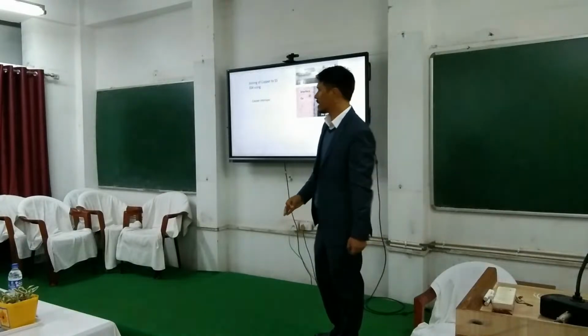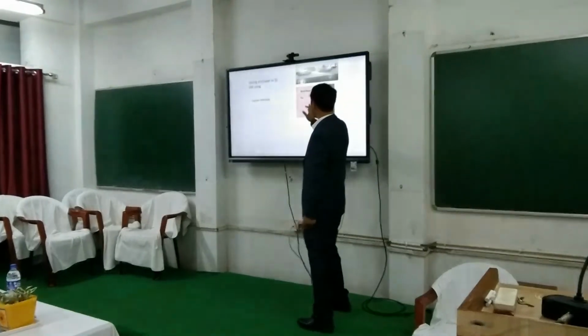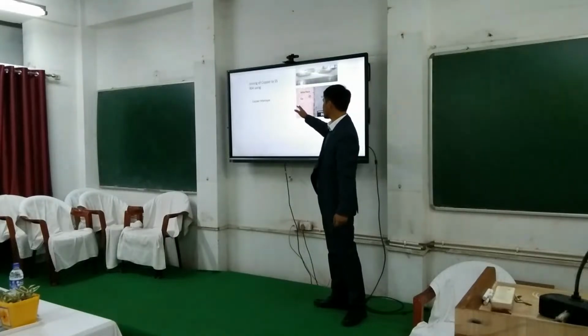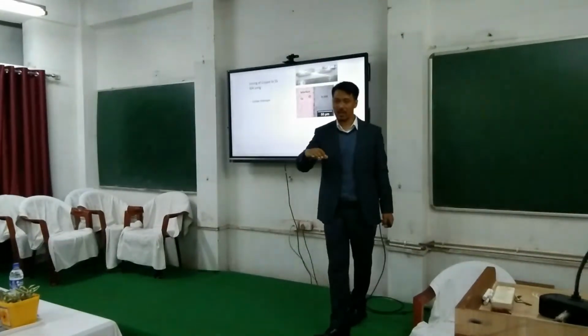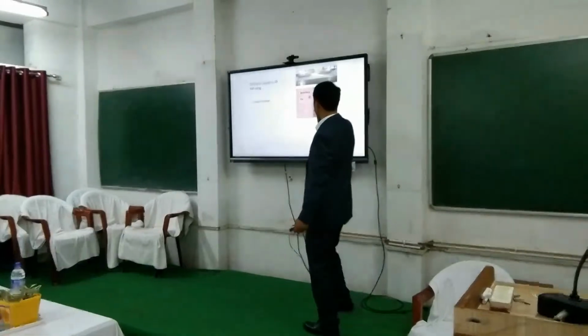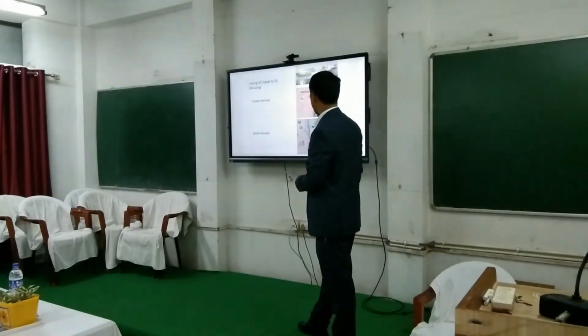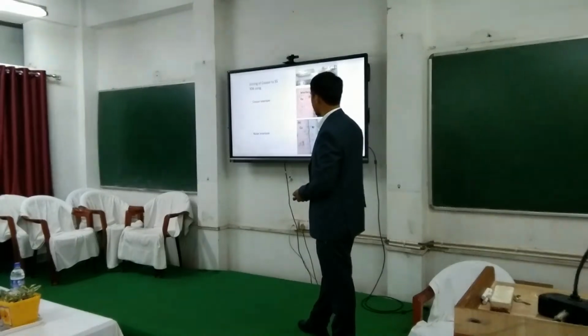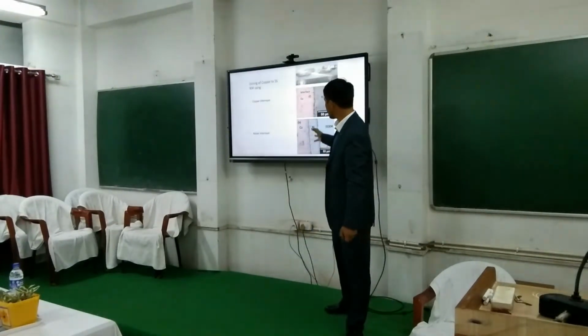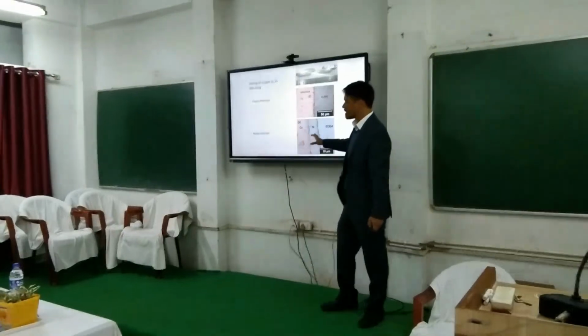A lot of diffusion is happening in a microwave joint, so diffusion between the interlayer and the parent materials. In this case, copper is one of the parent materials, and the interlayer is also copper. There is a seamless joint between these two. We can also use other high melting interlayers, like nickel, whose melting temperature is 1400 degrees Celsius. These also can be heated to that high extent, and we can form the joint between copper and stainless steel.